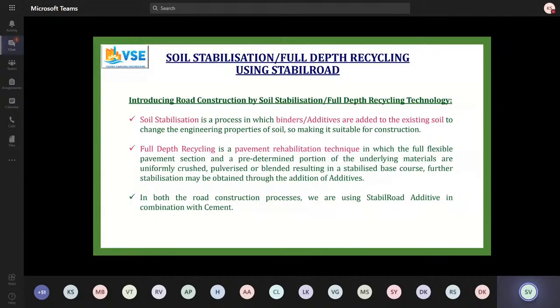Usually we scarify it and remove 30%, or in some cases we use 30% of the asphalt for recycling of the bitumen. Here we're not removing anything. We're using the same surface, and we're stabilizing the same.